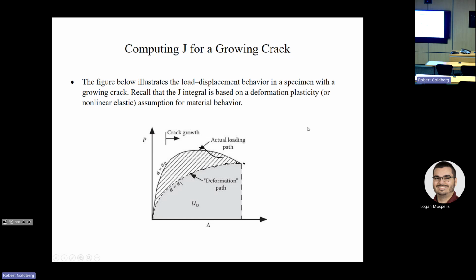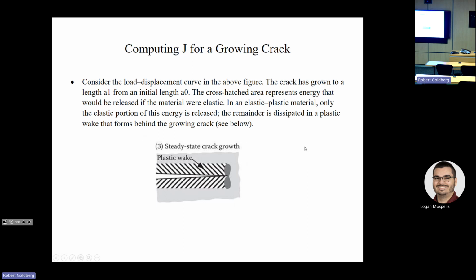So if you look here, we're assuming that the crack has grown to a length A1 from the initial length A0. So if the material was elastic, so this is our load displacement curve, the solid line. This cross-hatched area is the area that would be released if the material was elastic. Now, in an elastic plastic material, only the elastic part of the energy is released. The remainder of the energy is not released, but instead you have this plastic wake behind your crack, and this is what absorbs the energy for an elastic plastic problem. So this is just something to be cautioned about.